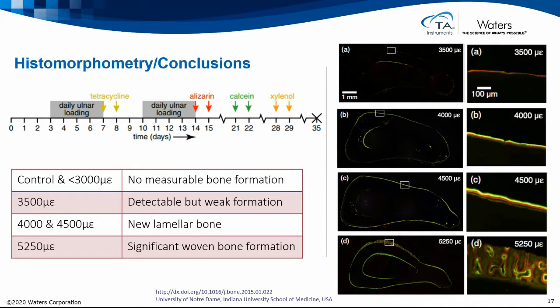And the table is essentially showing us here that less than 3,000 microstrain, we get very little bone formation. And now we get a little bit more at 3,500, and then at over 5,000, we see significant woven bone formation. So this is just a kind of a neat study on looking at the amount and the different types of formation of bone as a function of strain. And this study is just really nice and thorough on understanding how much strain is occurring at which part of the bone, and then sectioning it at that part of the bone to then look at this reaction and growth and remodeling as a function of the force.